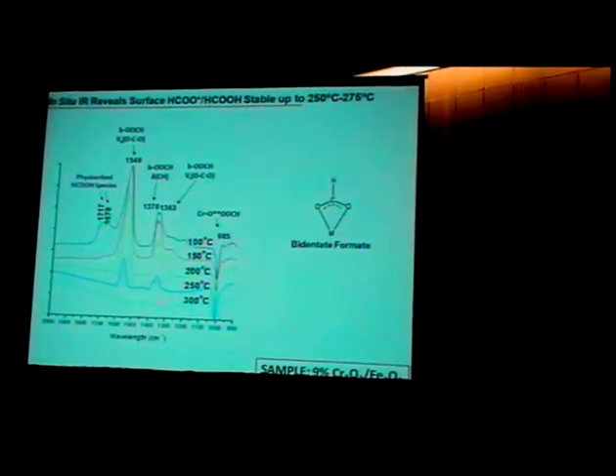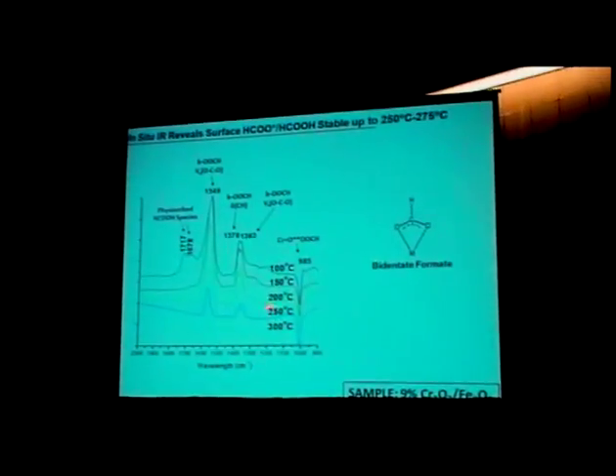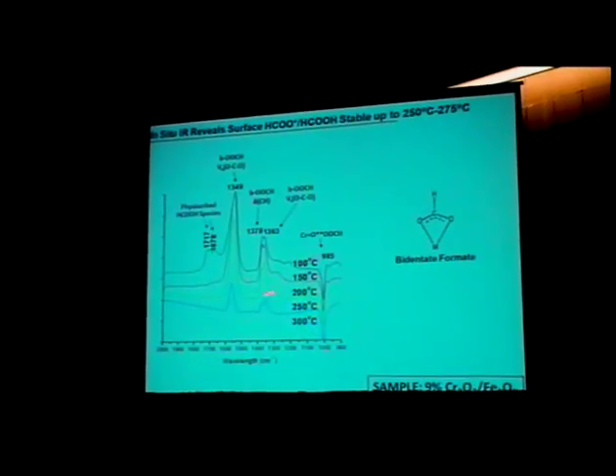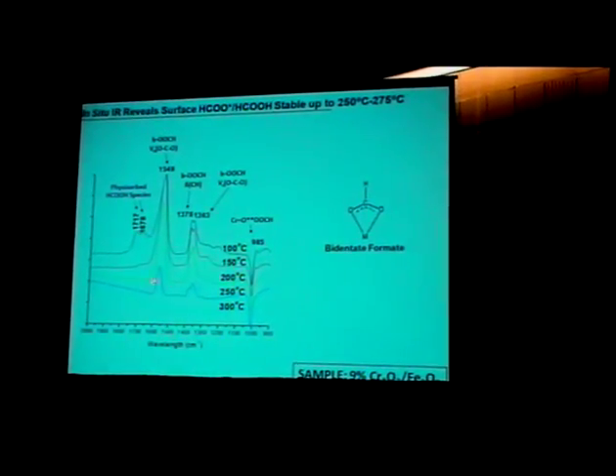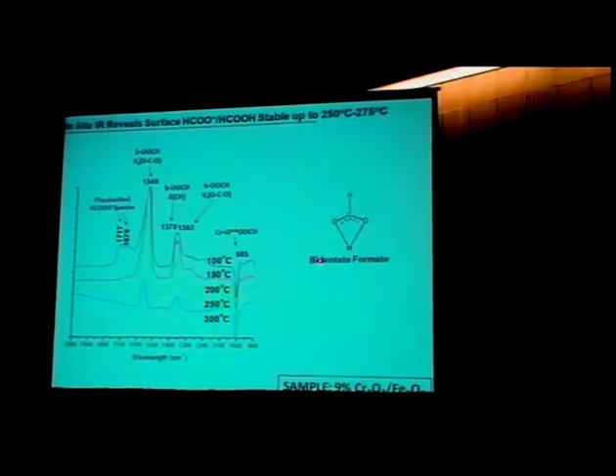which is the lower temperature range of the water gas shift. Actually, you can still get water gas shift, as I'll show you, in this temperature range. So now we know the vibrations. There are different kinds of formate on catalyst surfaces. There's monodentate, there's bridged, there's bidentate, and on the chromium iron catalyst, we have the bidentate form. And now we know its vibrations, and we're going to see what happens during a reaction.